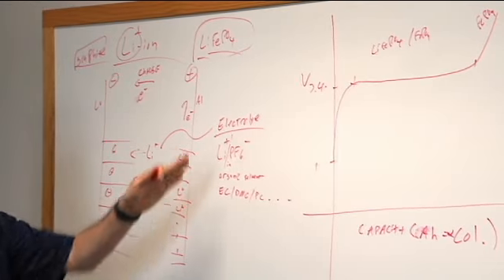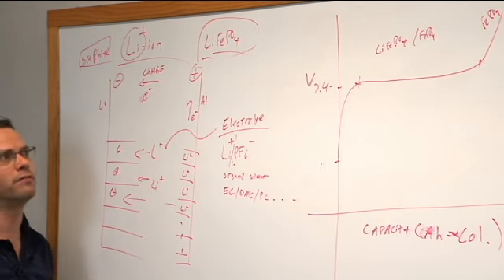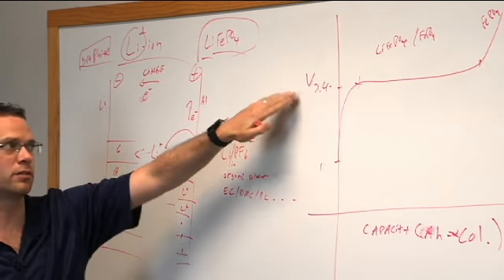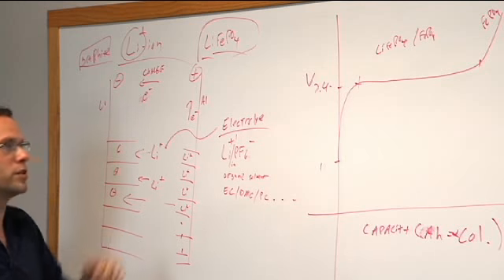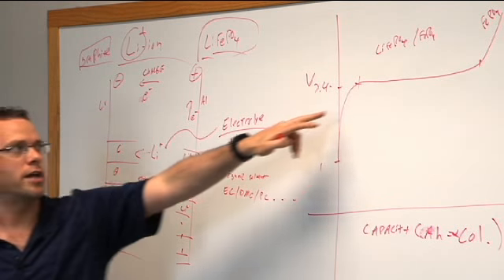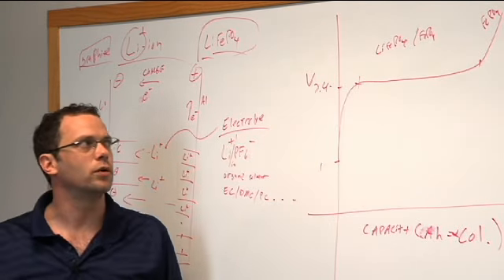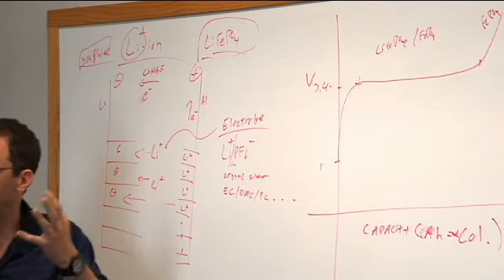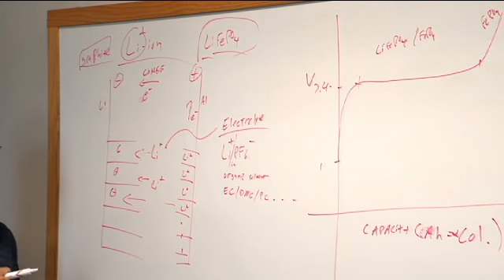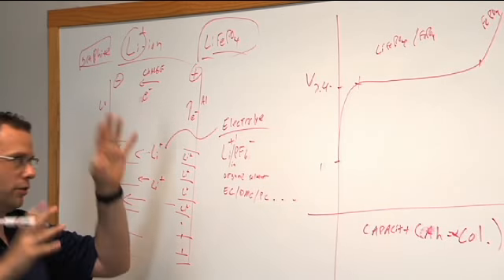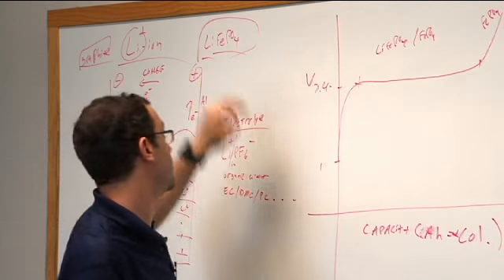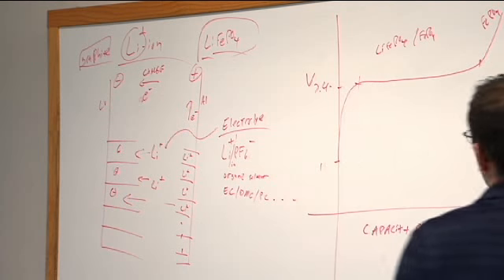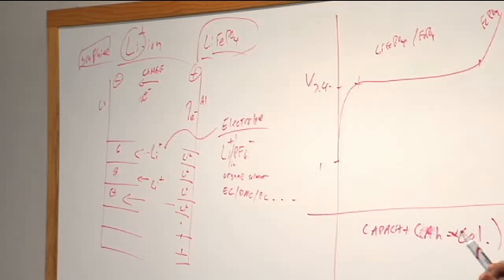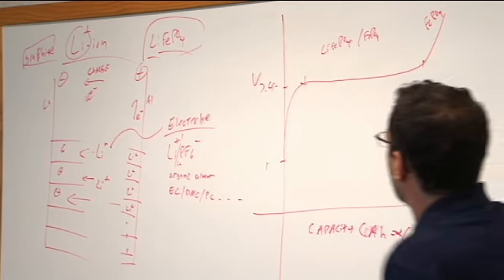And this is one of the reasons why people are looking to lithium iron phosphate for automotive applications, because by virtue of having this lower potential, the electrolyte is more stable, and there's much less chance of evolving gases that could lead to venting and combustion, right? So there's this trade-off that occurs. Plus, lithium iron phosphate is relatively inexpensive compared to lithium cobalt oxide. Cobalt is not so cheap, although there are many costs associated with fabricating nanostructured material that can still drive the cost up of any of these things very easily. So this is what's happening, right, on the charge.